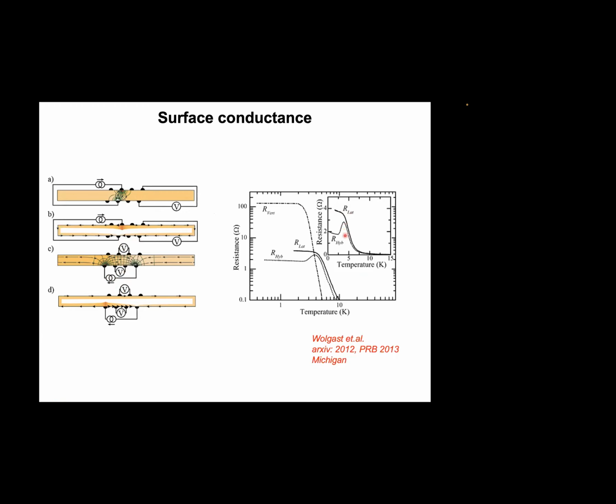As an experimentalist, I know that the location of contacts may not be precise. So in that sense, we always have a scaling between the typical resistance of the sample and the bulk resistivity of the sample with a scaling factor, right? But of these two traces, one is monotonic, the other is not monotonic. So clearly, there is a very strong anisotropy going on in this compound, in this simple cubic single phase crystal. So that shocked me.